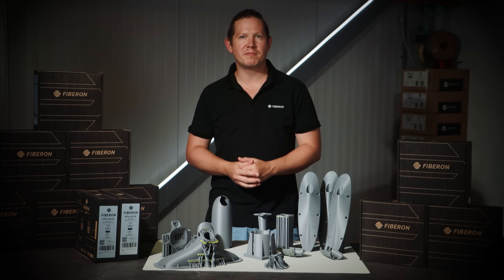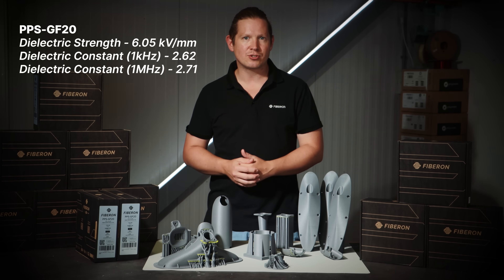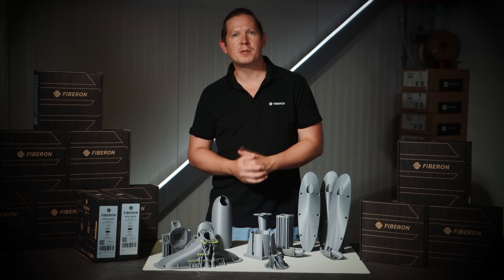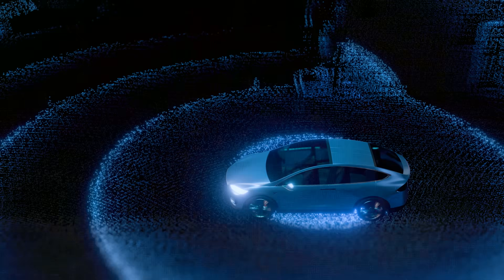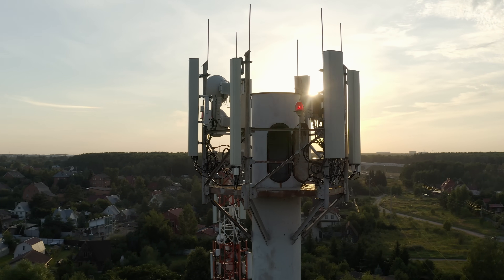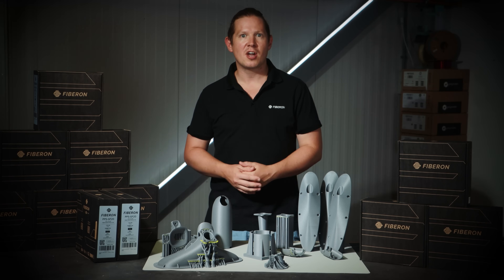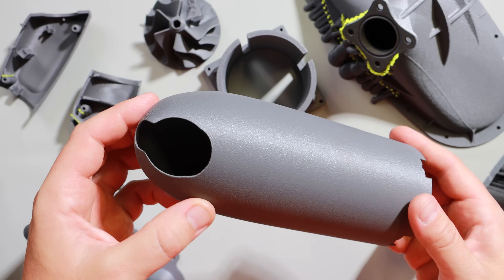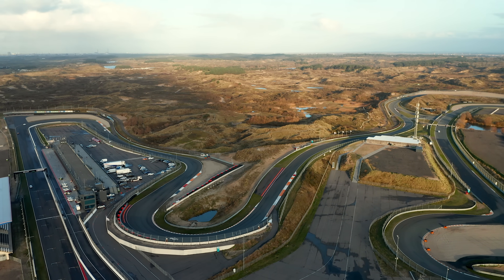Another great property of PPSGF20 is the electrical insulation, displaying excellent dielectric properties even at high frequencies and elevated temperatures. This lends PPSGF to insulative applications such as automotive radar systems, 5G base stations, or industrial antenna mounts and housings. There's also the added benefit that glass fibres don't block radio signals whereas carbon fibres do, which makes PPSGF the perfect material for high-end drone shells like this one, where stiffness and heat resistance need to be packaged into a lightweight shell.